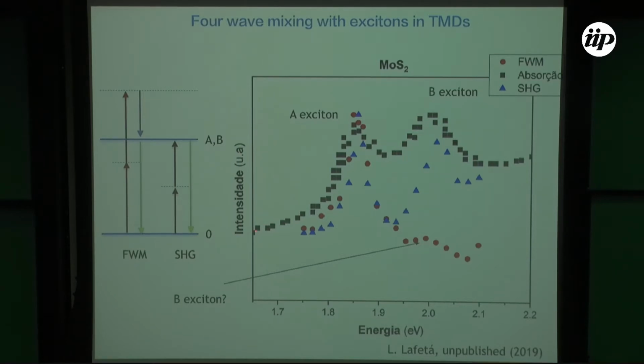So here's the MoS2. The black dots here are the absorption of MoS2. Here we have the first absorption, that's the A exciton, and another absorption peak here, that's the B exciton of MoS2. In blue here is the second harmonic emission, okay. So for the second harmonic, in this case, we have 2 photons, okay. So we put the energy of the laser close to half of the energy of the A or the B exciton, and then you generate second harmonic that is in resonance with the A or the B exciton on MoS2, okay. Then you also observe, following the absorption, that the second harmonic has a strong enhancement close to the A exciton and another enhancement close to the B exciton.